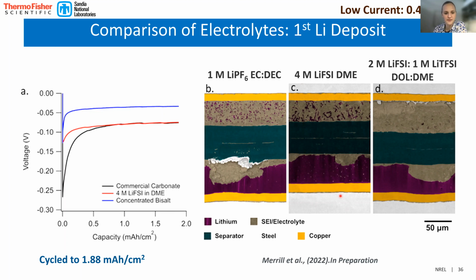With the 4 molar lithium FSI and DME, it actually had the least reaction with the electrolyte, and so you're seeing the least amount of SEI product, and it's the thinnest from the stack level. But there are large pits that formed in the counter electrode during the lithium plating, and the lithium grains are a bit larger, but there's still a lot of porosity there. In this concentrated bisalt electrolyte, you can see there's a lot of pitting in the counter electrode from the lithium, and there's not a lot of large lithium grains that formed on the working electrode.